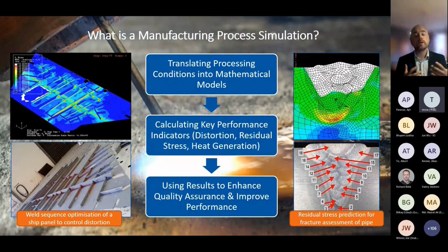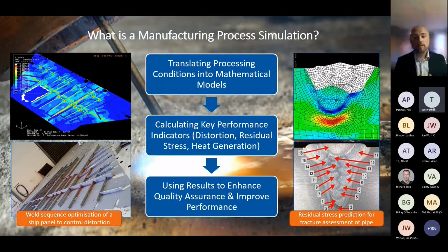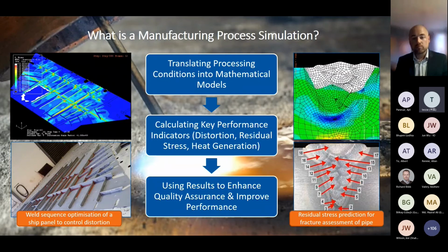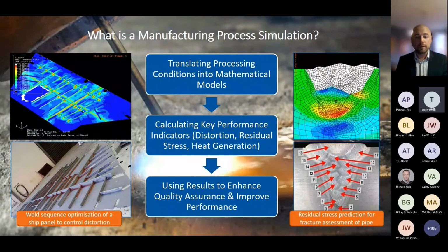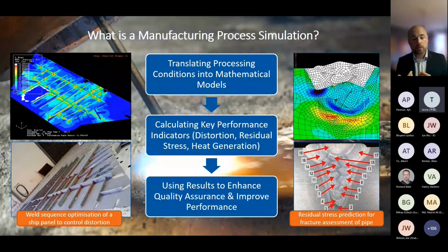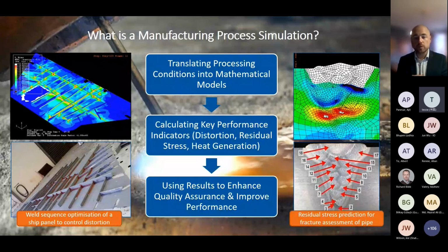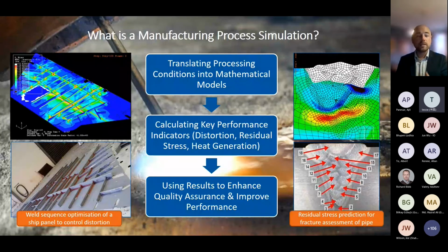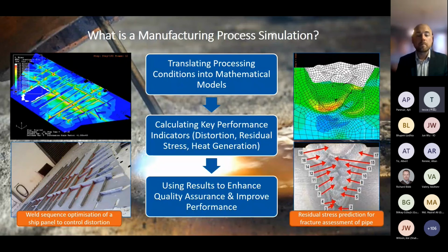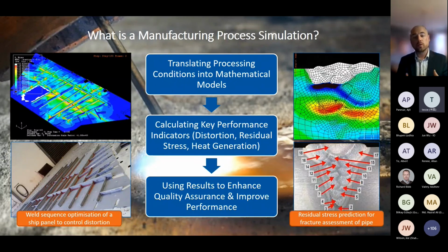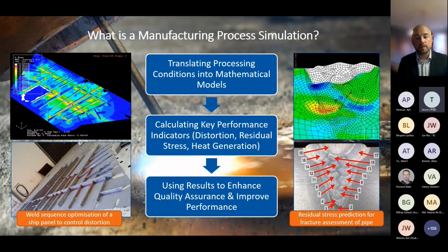But what we try and do is translate a process into a mathematical model, validate it, make sure we're confident in it, and then use it to calculate the key performance indicators. Could be distortion, like we were looking at earlier, could be residual stress, could be the buildup of heat in the thermal transients. And then we use those results to go back and improve the process itself.